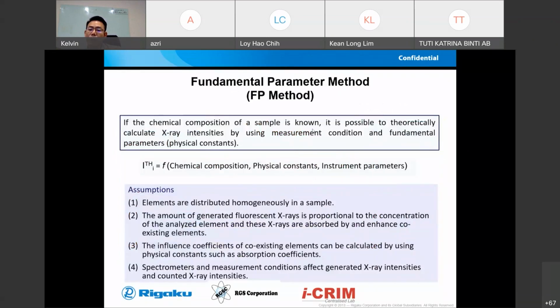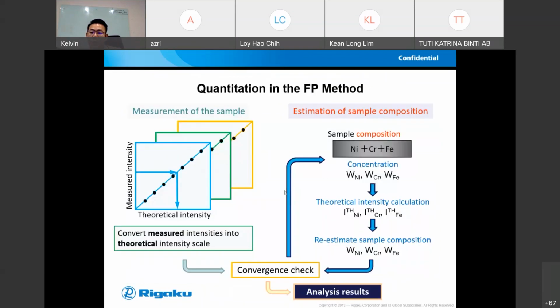But also, one thing to remember: before that, there's an assumption. The assumption is that before we use the FP method, the elements must be distributed homogeneously in the sample. This can easily be done as long as you grind the sample to 75 mesh and below. You can create a very good homogeneous sample. But there are a few things which are very difficult for us to do, for example, some of the light elements that are not possible to measure in the XRF if you don't have that particular crystal.